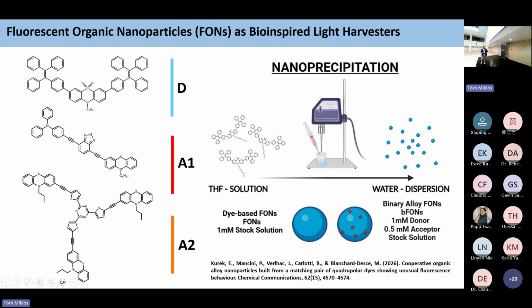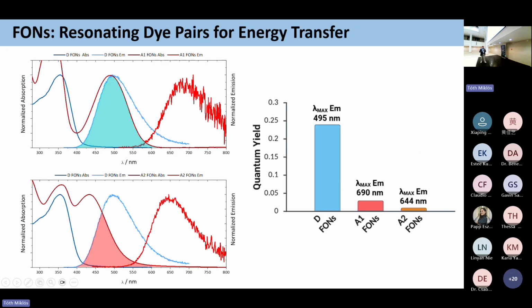In particular, a stock solution in THF of the dyes is rapidly injected into a large amount of water under vigorous ultrasound sonication provided by a probe-equipped processor. When in water, the molecules find themselves in a bad solvent, so they spontaneously aggregate into self-organized particles. When we made the single component FONs, we saw that there is quite a large spectral overlap between the donor's emission and the acceptor's absorption spectra. So we thought, okay, we can try to put the dyes together in a single particle to see if we can exploit an efficient energy transfer between the dyes.